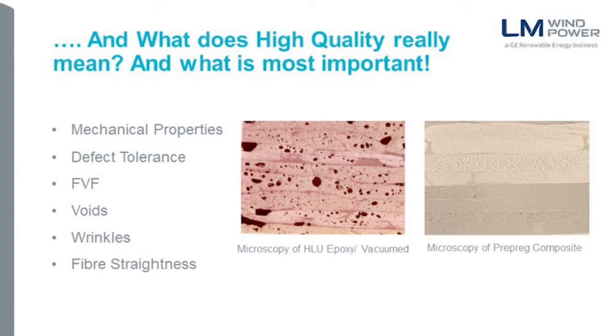I've got an interesting little comment about void content and degassed resin. So degassing is a process we use for resin infusion, and I think RTM as well a little bit, where we get the resin we're about to infuse or inject with, and we put that in a pressure vessel and boil it at room temperature to reduce the pressure above the liquid to get all of the entrapped air out of the resin, and it looks like it's boiling. If you do it in a clear vessel, then you look at the resin, it looks like it's boiling. And degassed resin, from an infusion perspective, gives you a very clear, high quality infusion. It helps your infusion, but it's expensive because you've got to put your liquid into a vessel to degas it for a period of time at a certain pressure before you infuse it.